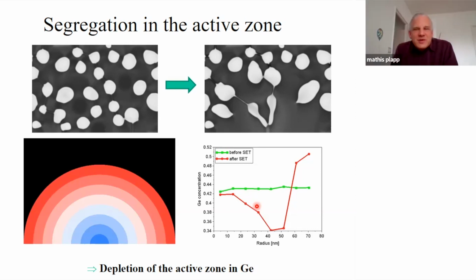Well, let's say if we want to have a real quantitative model, there is work for at least 20 years ahead. So that's not our goal. Of course, even in its current state, the model can be used to do some parametric studies. So for example, what I have shown is the set pulse. That is the pulse that makes the material crystallize. We have also done simulations for the other pulse, which makes the material amorphous. So the only difference there is that the current pulse has a different shape.